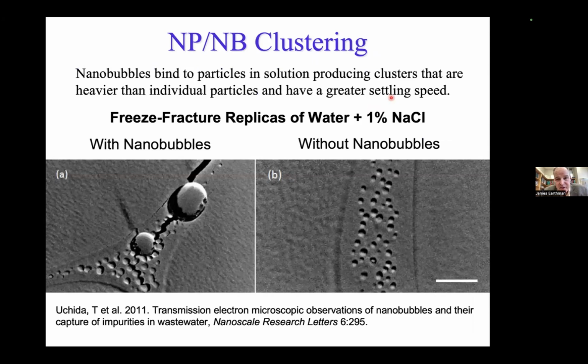Here are some freeze fracture replica images of some nanobubbles and nanoparticles that were published by Uchida and his group. You can see here, this is for 1% sodium chloride. So these are sodium chloride nanoparticles here. This is just with the nanoparticles, with the sodium chloride without the nanobubbles. And here you can see the nanobubbles, a pretty clear distinction, and you can see the nanoparticles are binding to them.